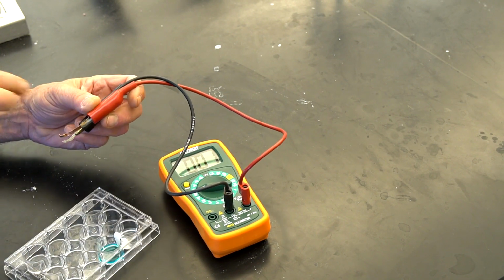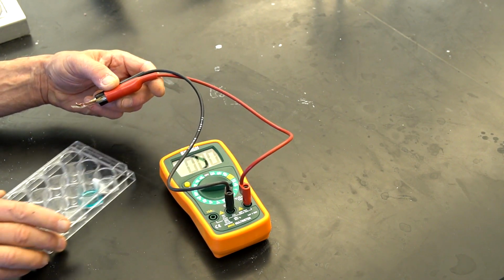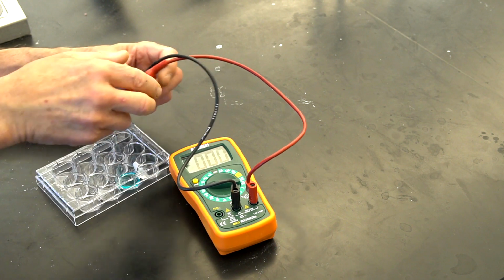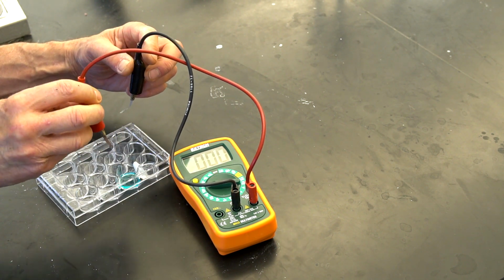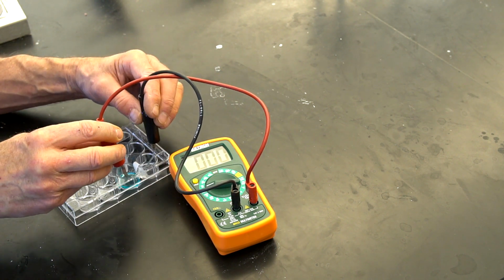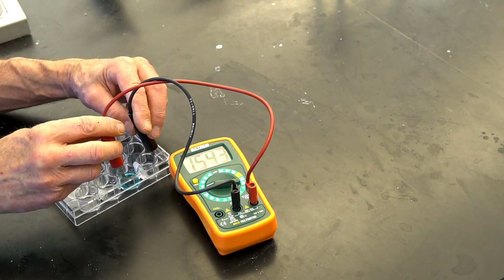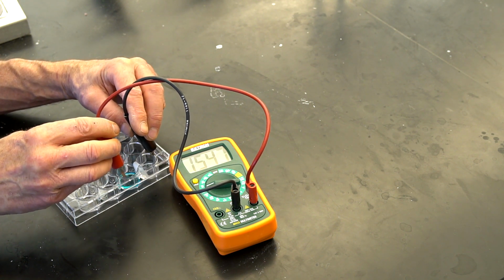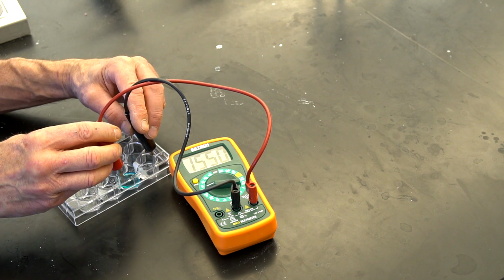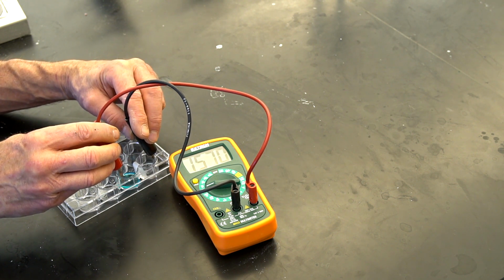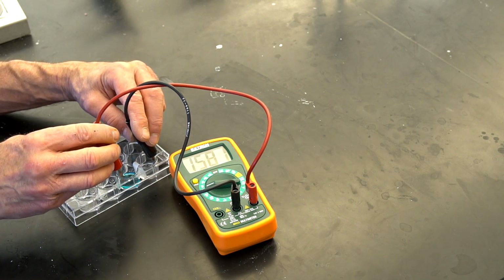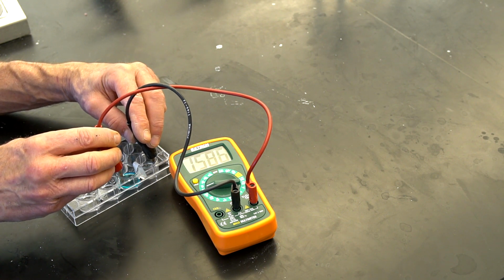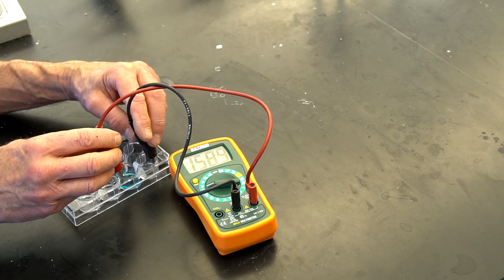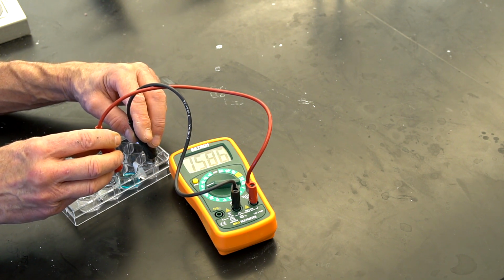So we have copper and magnesium, and we're going to dip the copper electrode into the copper solution and the magnesium electrode into the magnesium solution, connected by a salt bridge, and we can read a voltage of about 1.56, let's call it 1.6 volts. So the combination of magnesium and copper has produced a very, very large voltage relative to the others.